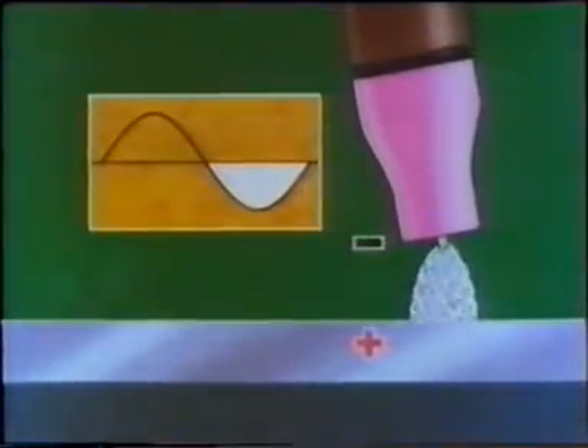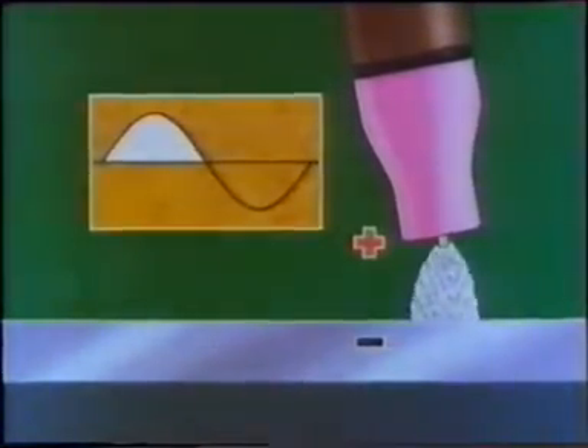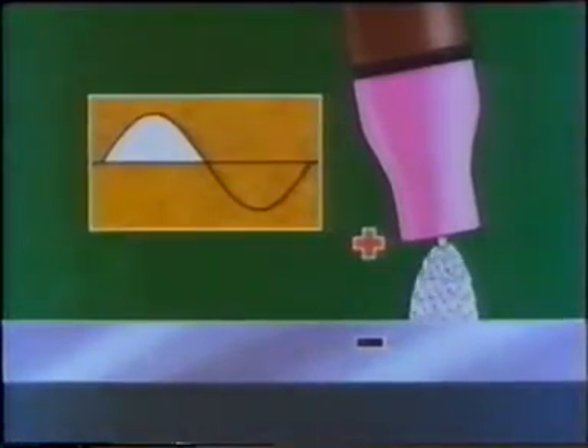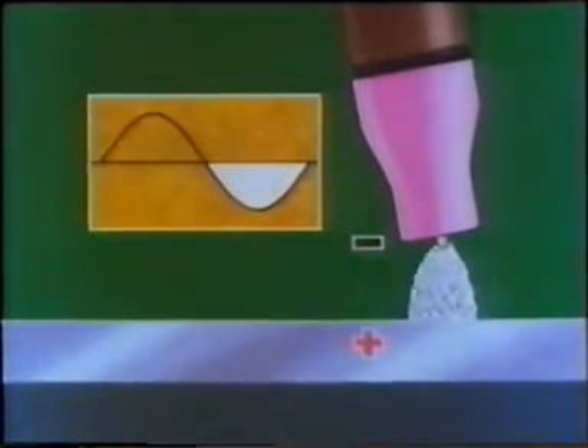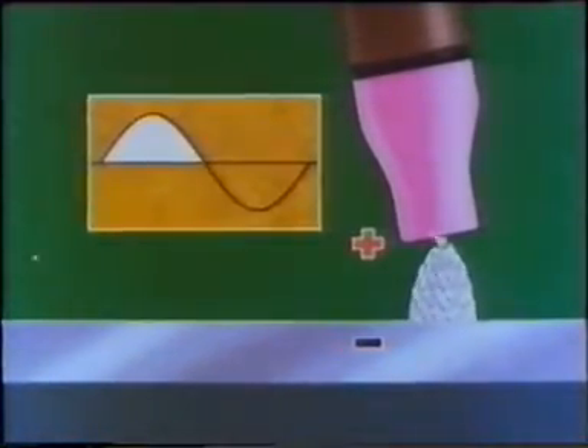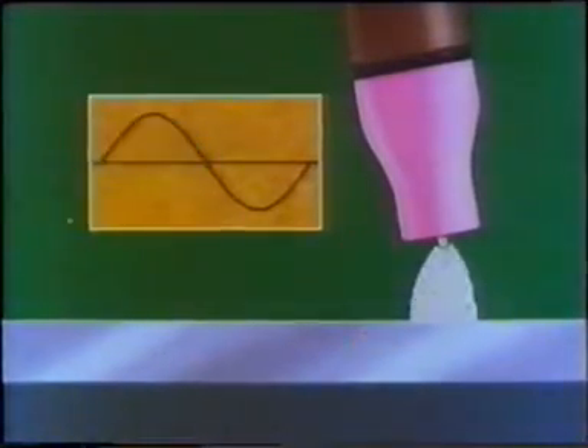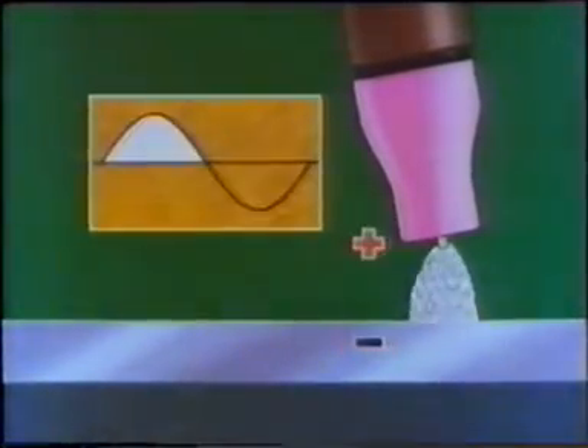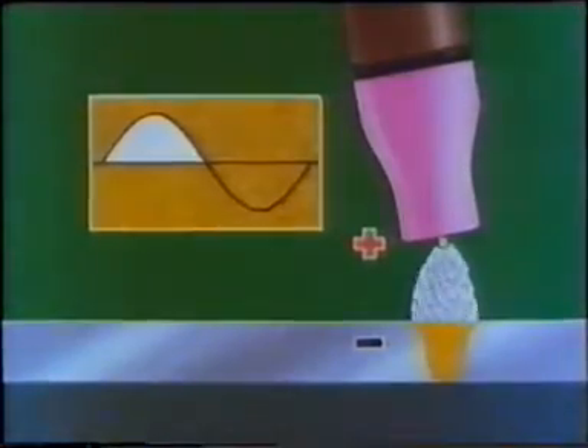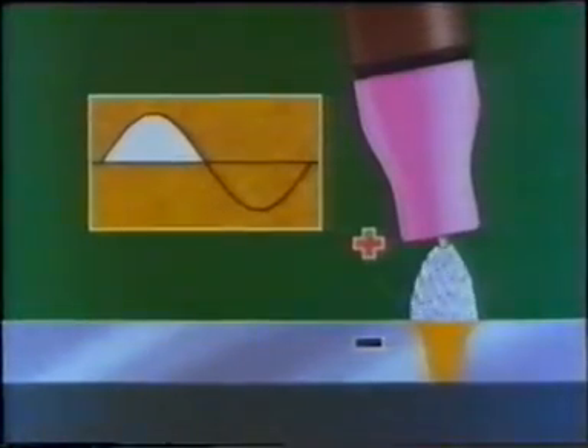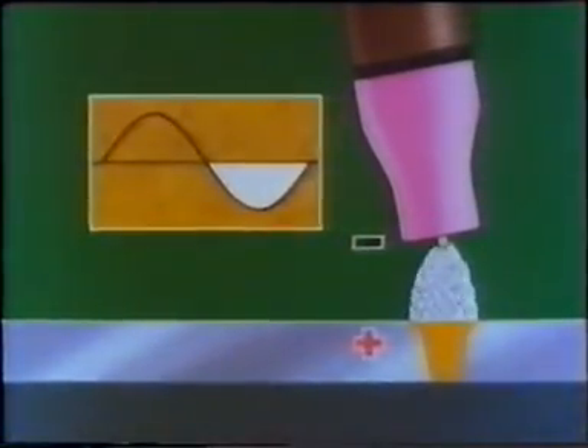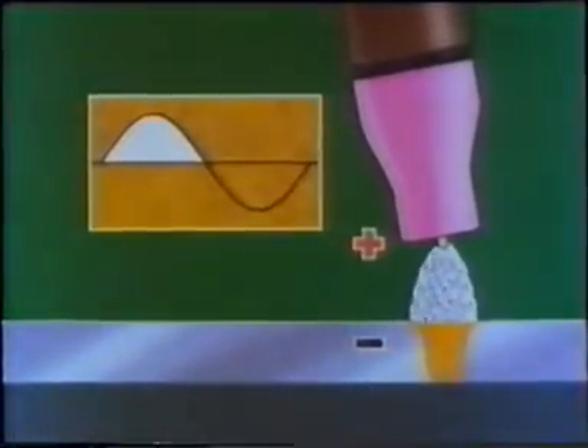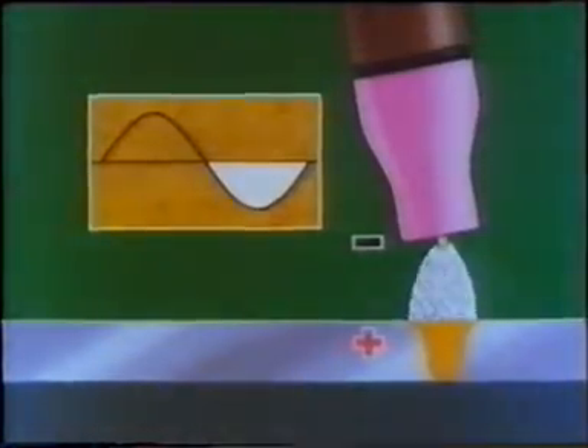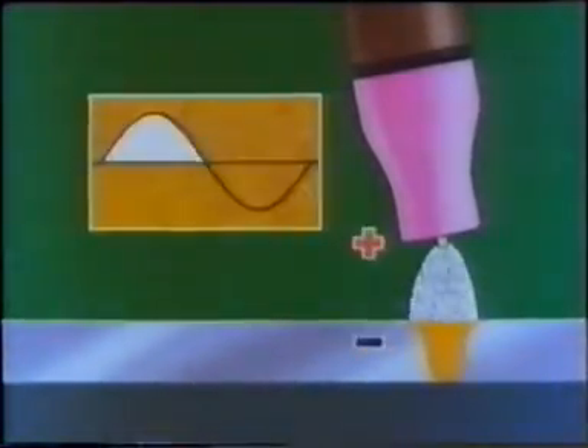Negative electrode to bombard the job and break the oxide up. Positive to lift the oxide off. Negative to heat the job. Positive to lift the oxide off. And so on until deep, narrow penetration is achieved. The electrode heats up, of course, on positive half cycles, but cools down again on the negative half cycles.